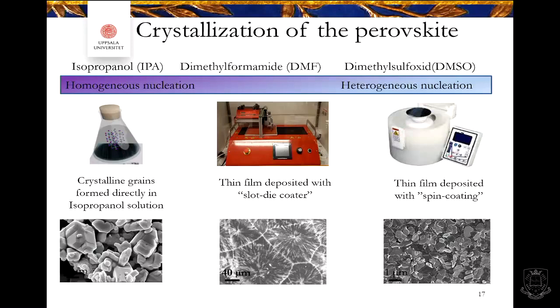And here you also see examples of different solvents that are normally used in solar cell production. So DMF is rather toxic, you want to avoid that, but it's still there in many cases. And then we try to go over to DMSO instead, which is less toxic, but it's still a little bit toxic. For instance, DMSO is used to transport atoms from the outside to the inside of the skin. On horses, for instance, when they treat them with medicine, they put it on the legs with DMSO, and the medicine goes into the body. So there we have to be careful when we work with that and have lead iodide, for instance. So even though DMSO in itself is not so toxic, it can cause things that are toxic.